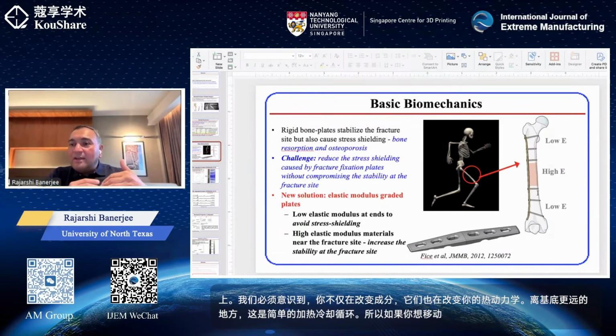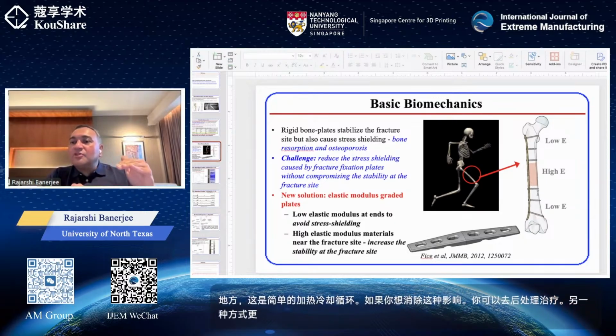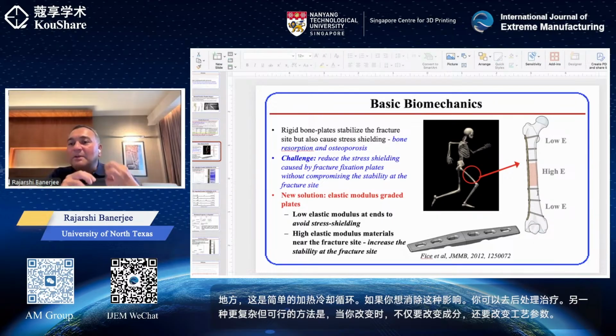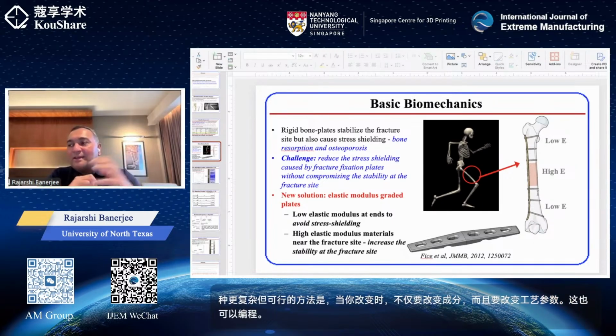The other way, more complicated but doable, is that not only do you change the composition, but you also change the process parameters when you're changing from one composition to another, which can also be programmed in to try to get back to similar thermokinetics in each layer. It's not easy, but it is possible. So those are the two approaches that we have done.